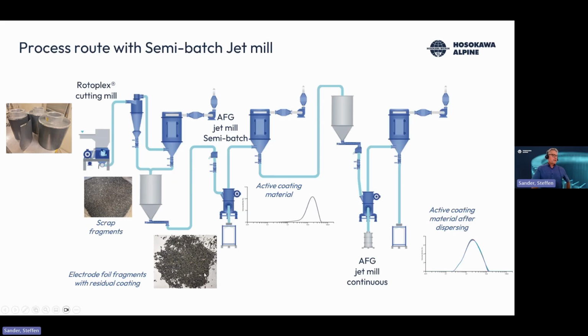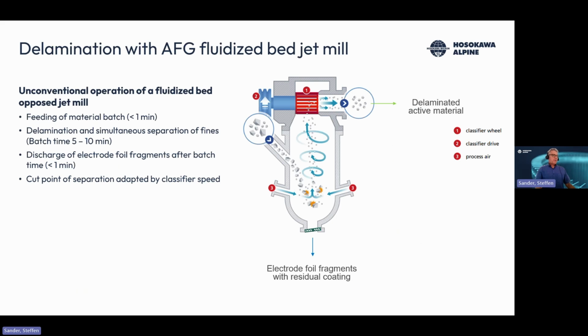Again, you can see the electrode fragments that come directly from the first jet mill have some residual coatings on top, but you have the separation during the delamination in this case, and we've seen that the yields are a bit better using this process, and also the tendency to form impurities is lower using this semi-batch mode jet mill here. You can see how this works.